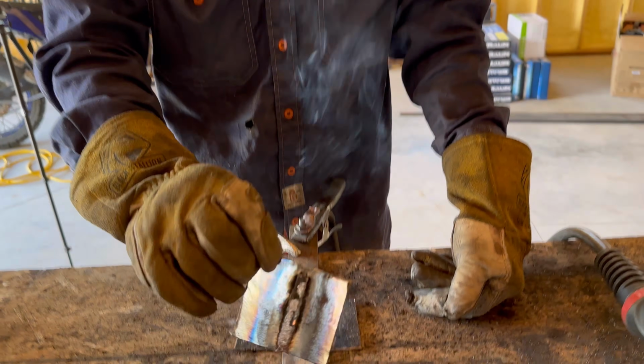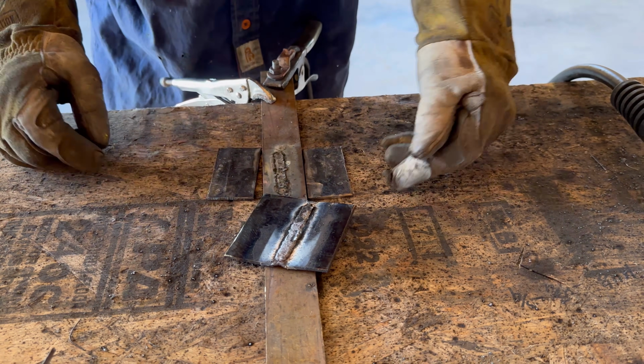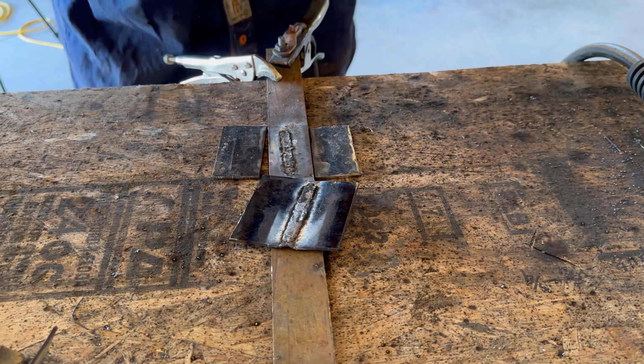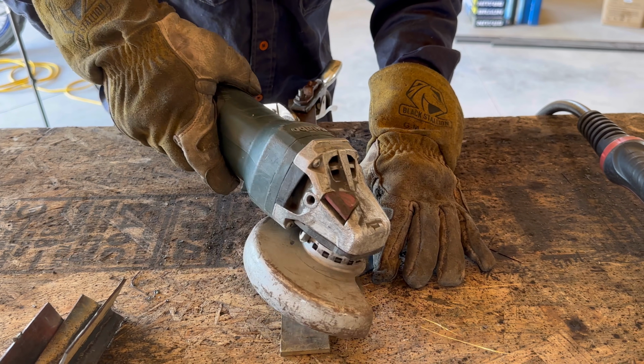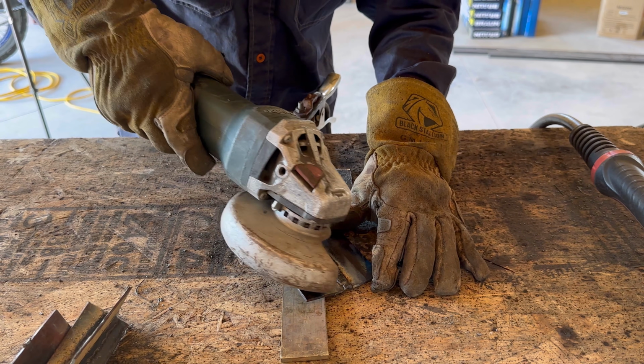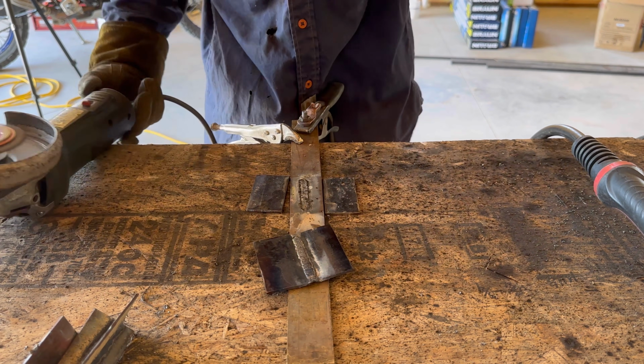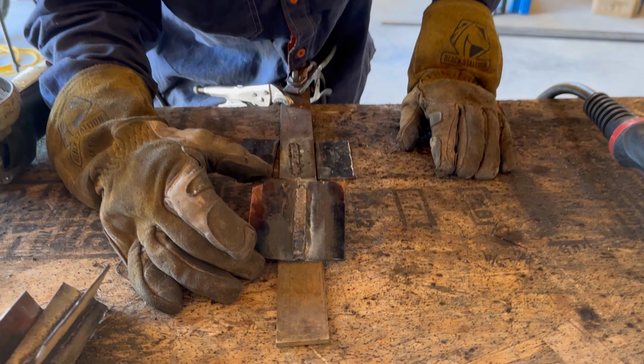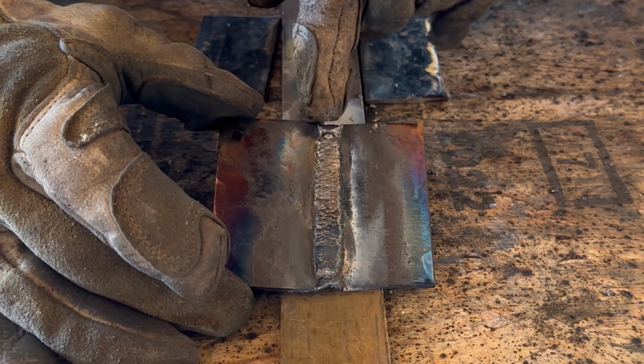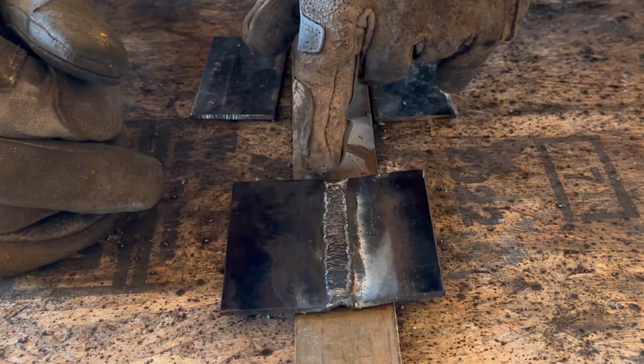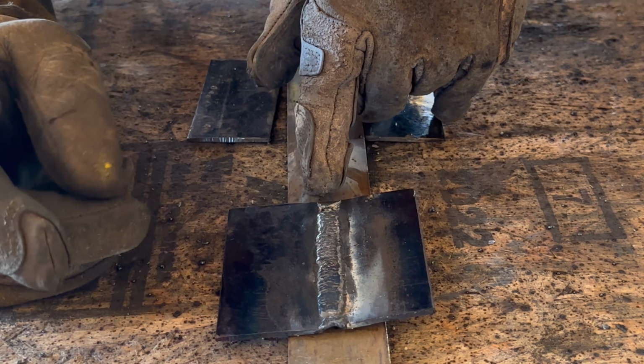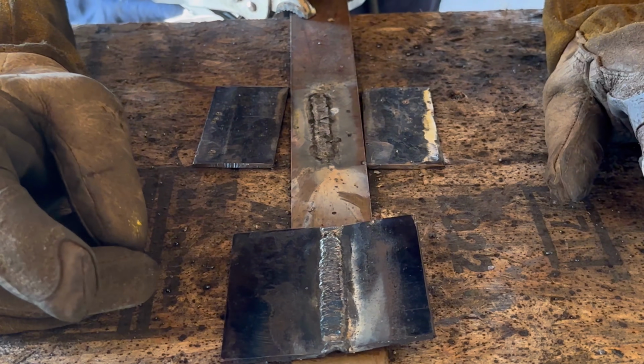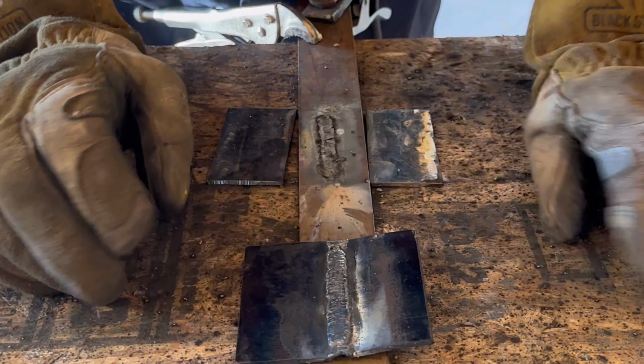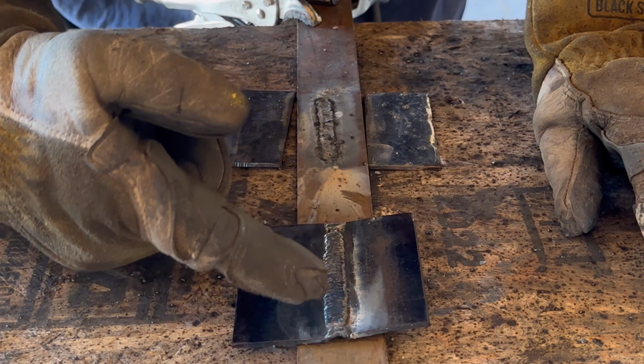As you can see, it doesn't stick to the copper backing bar. And there's the back side of the weld. Let's clean that up so I can get you a closer look. So that's the back side of the weld right there, and it doesn't look half bad. You can see I made a mistake there at the start. That was a cold start, and that's what I was talking about earlier, and that's what you're trying to avoid by whipping back in, and I didn't do it this time. So, as you can see, I faced the consequences of that. However, the rest of the weld looks pretty good.